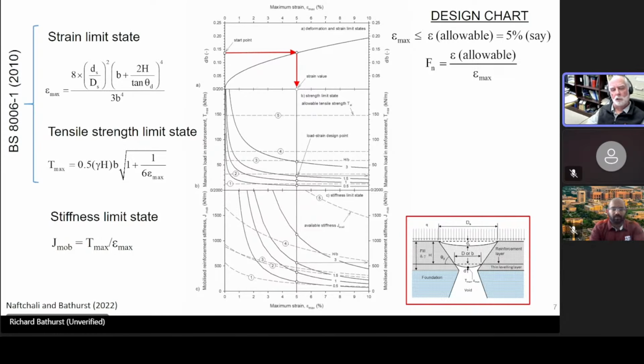And if you have a strain that's greater than an allowable value, you can calculate a nominal factor of safety. Once you have passed this limit state, the strain limit state, then one goes on to investigate the tensile strength limit state. And depending on the geometry of the void, one can then calculate what the maximum tensile strength in the reinforcement is. You can compare that to an available or allowable tensile capacity. And again, that gives you a nominal factor of safety.